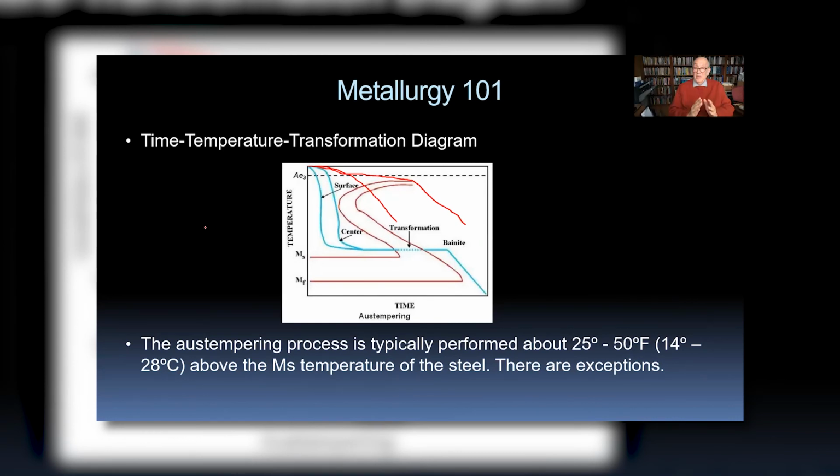So as a result of that, you have to move very rapidly where those turquoise lines are shown. You're cooling at a very, very rapid rate to try to miss the nose of that transformation curve. The secret with Austempering is that you have to put the brakes on before you form martensite. And that's not as easy as you might think it is. But that's one of the reasons why molten salt is an excellent medium to quench into.